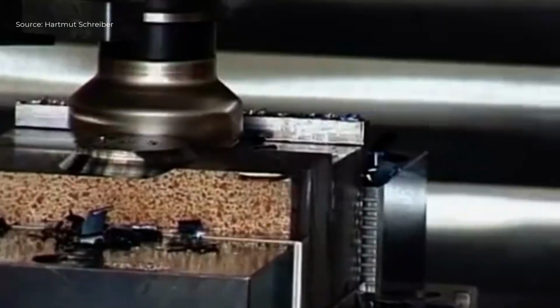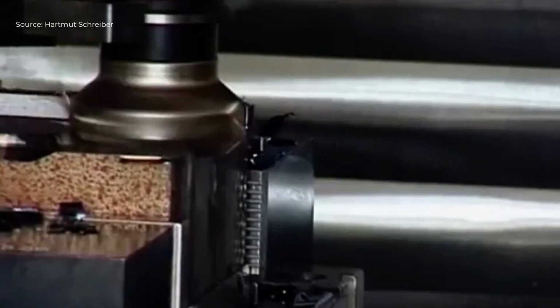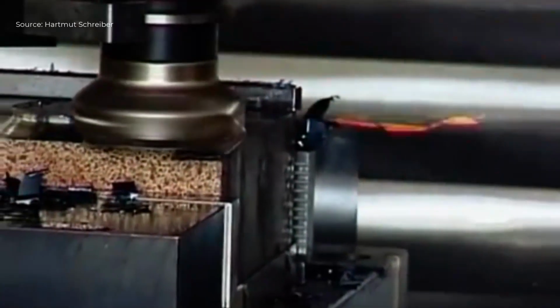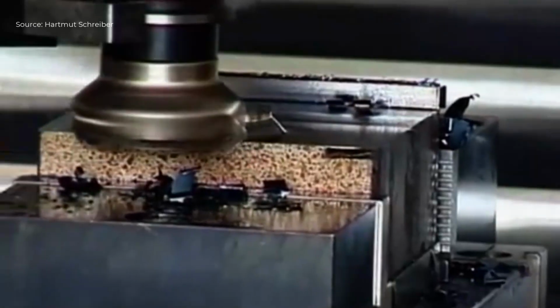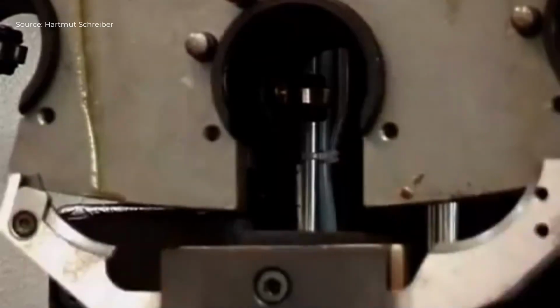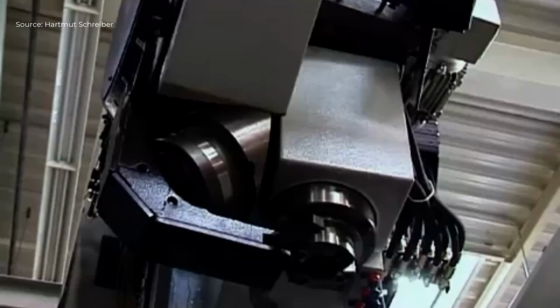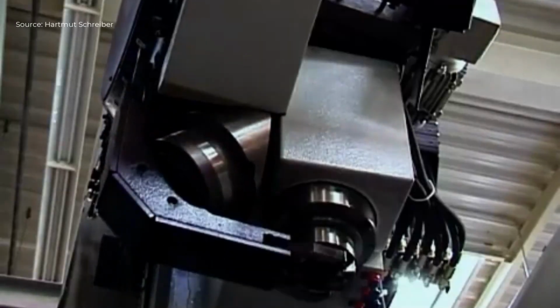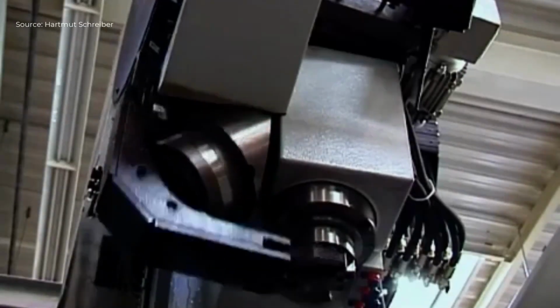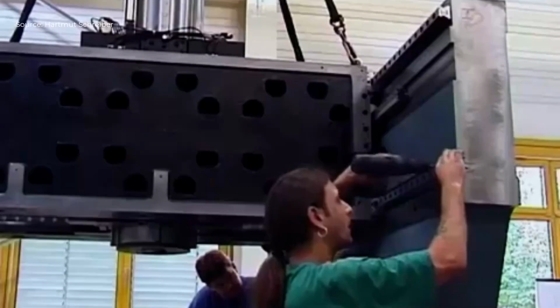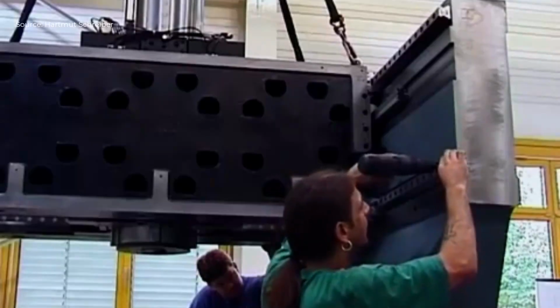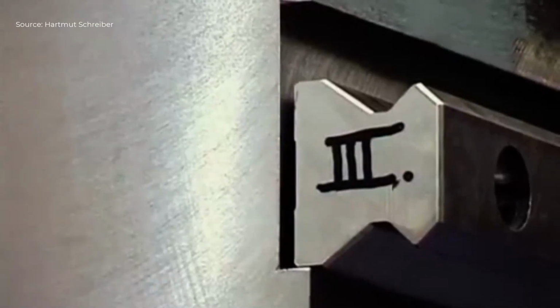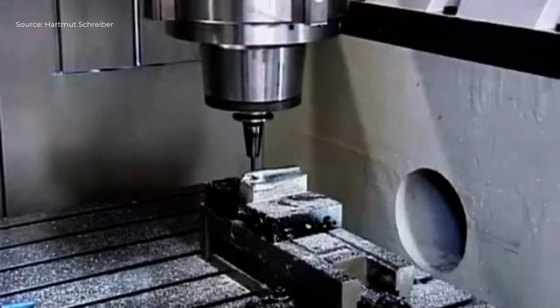Drilling machines undergo performance tests to determine their power curves during drilling and tapping, including non-cutting processes like flow drilling and thread forming. A computer-controlled vertical drill is shown performing high-speed milling using a carbide-equipped milling tool, reaching material removal rates of 1,000 cubic centimeters per minute in high-strength steel. A tool change is performed, followed by contour milling with a carbide milling head.